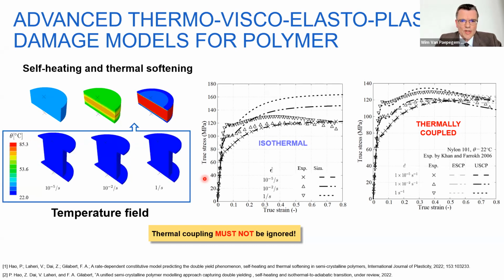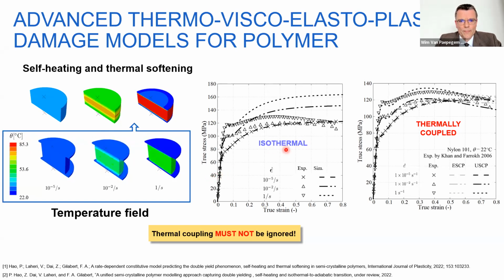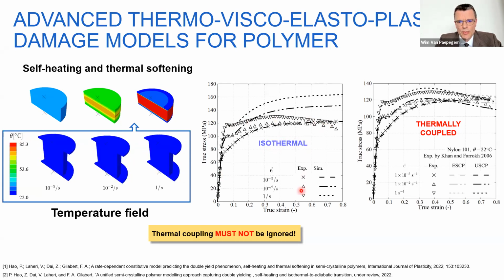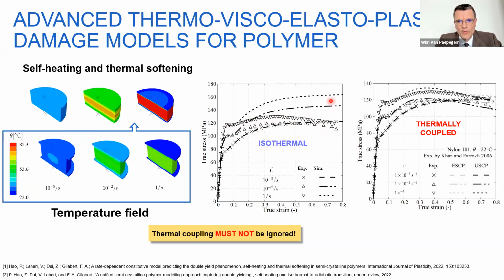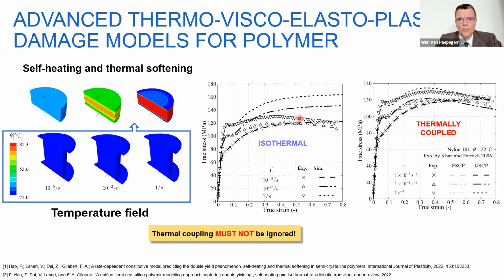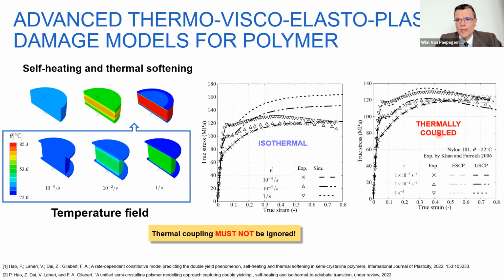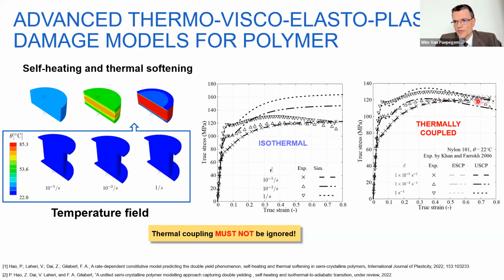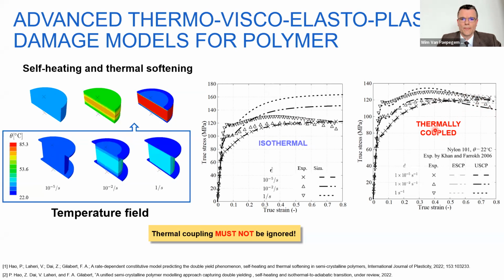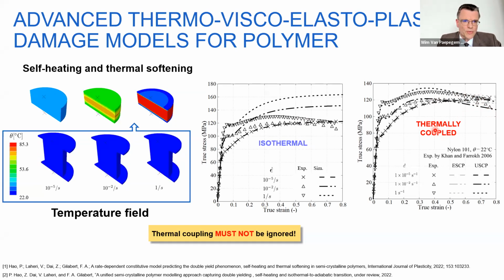And then you see that if you would approach your modeling with an isothermal model and you try to predict the experimental data, the experiments are in these symbols at different strain rates, you see that we overpredict the behavior a lot. While if we take this thermal coupling into account, we can see that at the higher strain rates, we get this softening behavior due to the temperature. And if you take that into account in a physically correct way, your model is also more accurate.